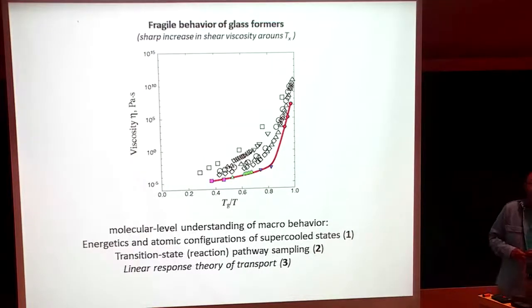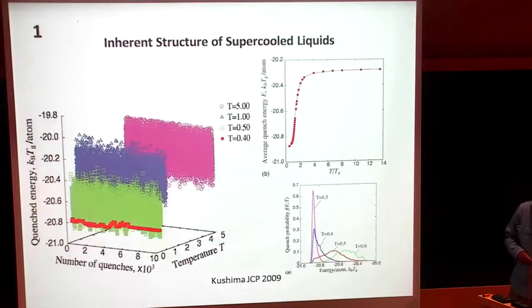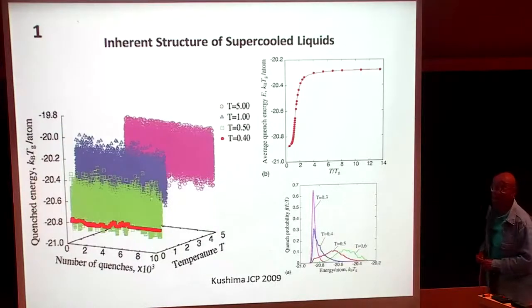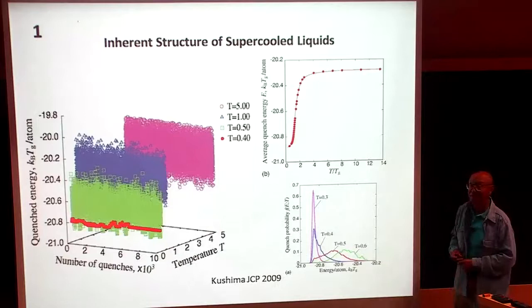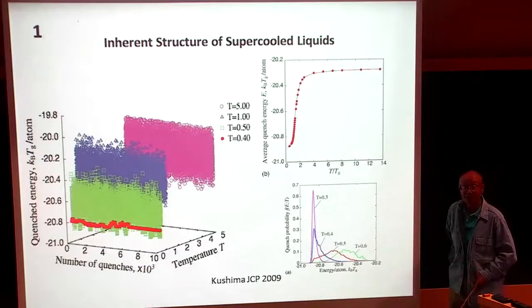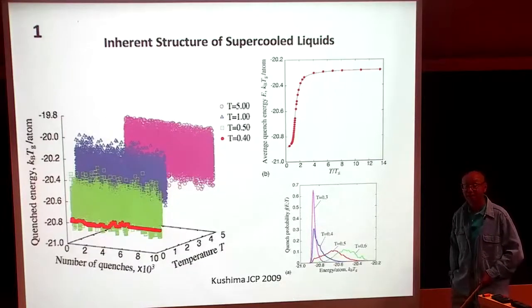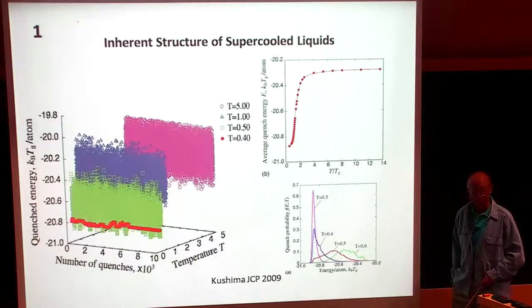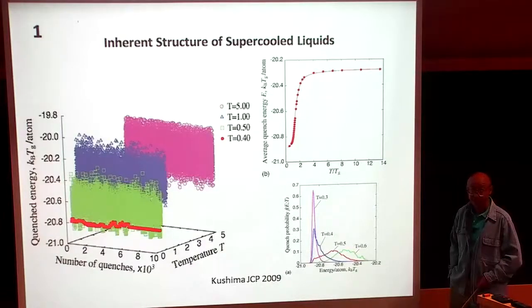That T equal to 5 is an equilibrated system from which you get the inherent structures by quenching. The T equal to 5 is not a quenched system. It is an MD completely equilibrated system, and then you quench to 0 temperature to get the inherent structures. So basically, you essentially get rid of the kinetic energy. Right, but the point is it's not stuck in any state. It's equilibrated. Yeah, but at high temperature. The assumption is that you're sampling everything and you're calculating the inherent structures.